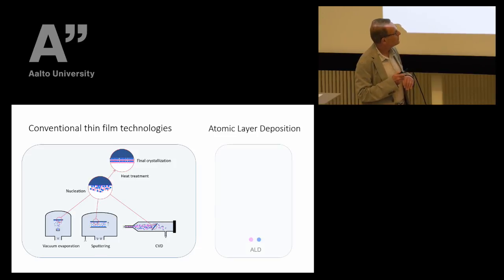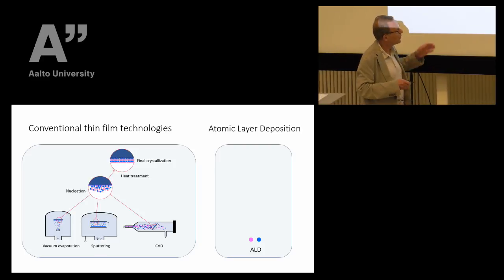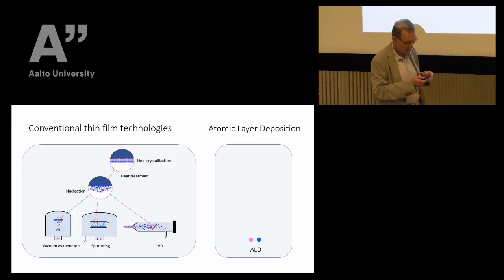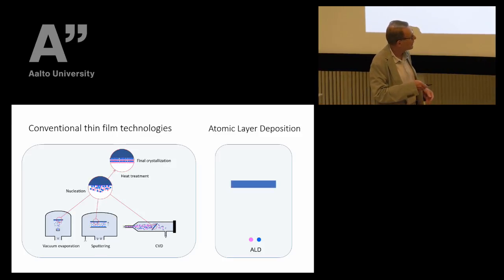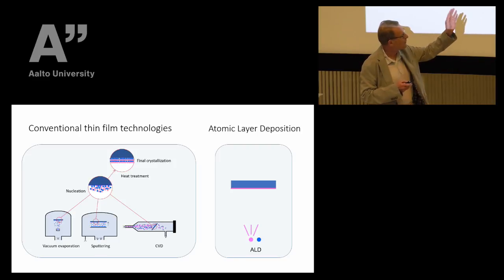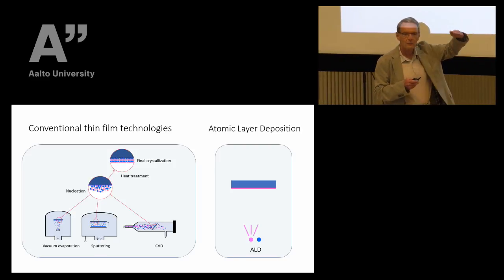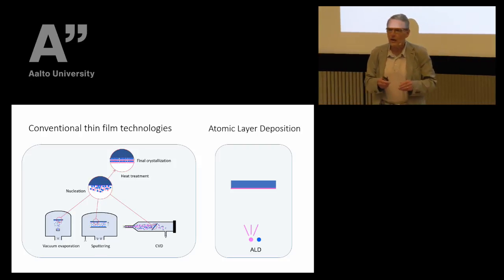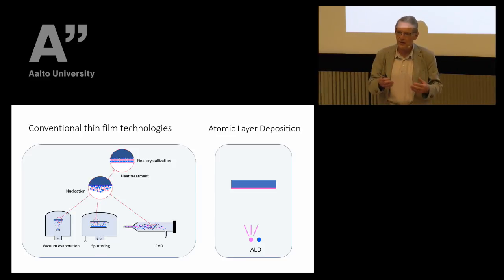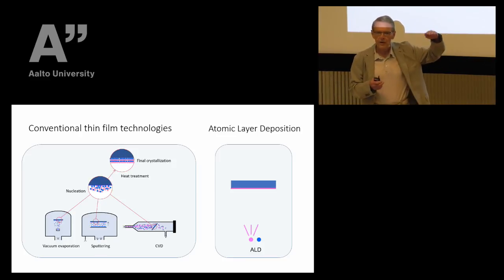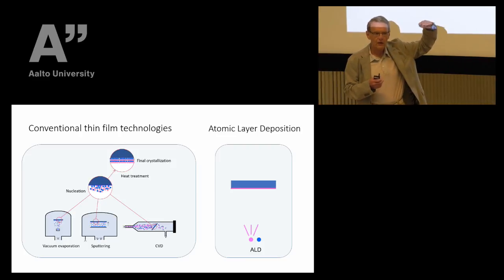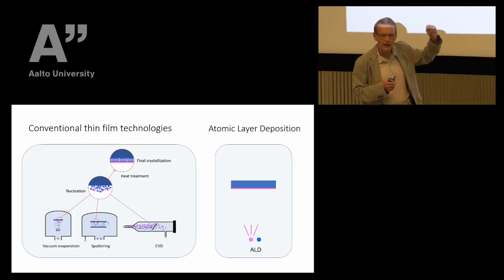With ALD, we influence the build-up mechanism. So instead of going the whole way from a disordered phase to an ordered phase, we start with the ordered phase. So we offer making a compound of red and blue materials. We start with one of them only, and in the case of the blue atoms, if the red atoms can find the blue surface, they stay there. So in fact we are creating conditions where nature takes care of the control. So we create conditions where the only way of getting one atomic layer fixed on the surface is that it finds a compound bond which is strong enough to keep it there.